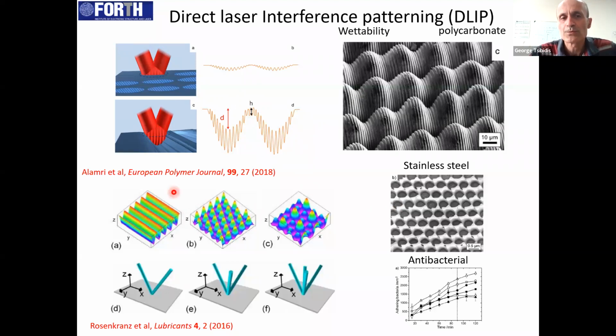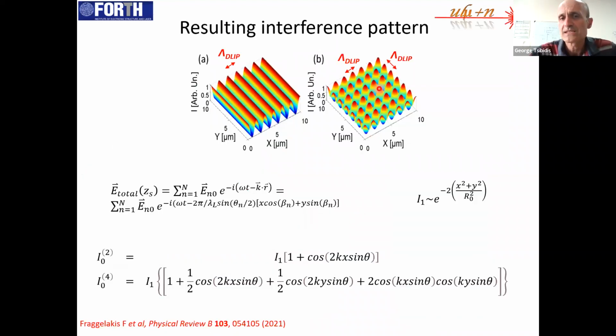in the shape of the beam. So depending on the number of the beams and the incident angle, we can end up with these three, for example, here, intensity profiles. So this is very interesting because this gives rise to the possibility to control even further the intensity and, of course, to produce complex structures. So this is the intensity. For example, here I have two beams, and this is the intensity after I used four beams.